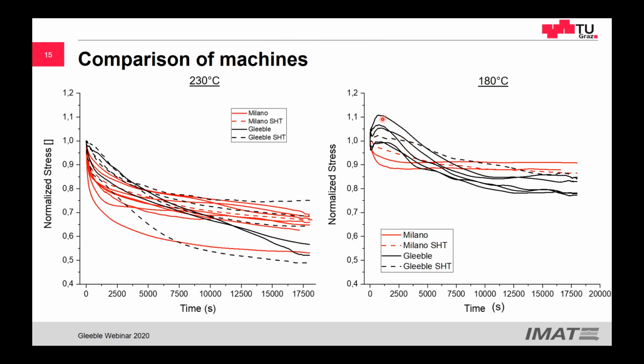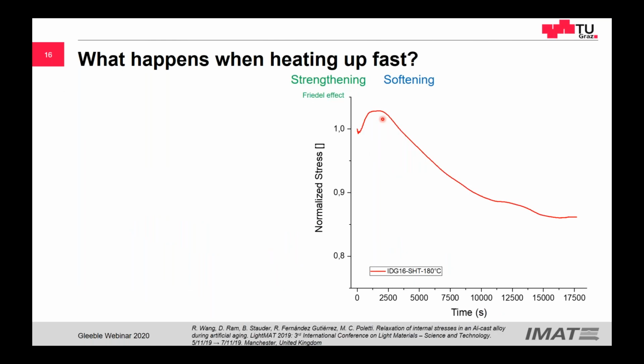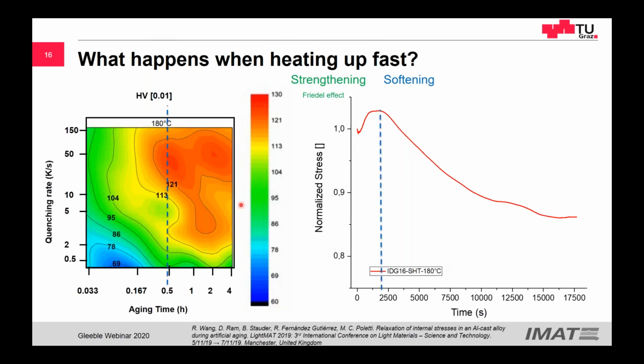And this comes because the heating rate is different. If we heat up very slow, we may have all the precipitations happening during heating. It takes up to 1 hour for heating, and this is too long. While if we can heat up very fast, we may see first the strengthening and then the relaxation of the material. And this is very interesting. So we can see that the stresses go up and then down.